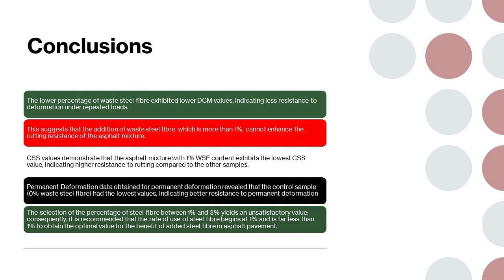Data obtained for permanent deformation revealed that the control sample, which is 0% waste steel fiber, had the lowest value, indicating better resistance to permanent deformation. However, as the percentage of waste steel fiber increased, the permanent deformation also increased. This suggests that adding waste steel fiber may harm the asphalt mixture's rutting resistance and long-term performance. Based on a previous study, using a range of less than 1% is recommended.